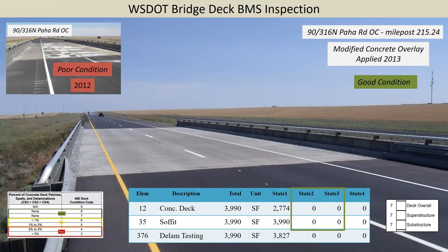This comes in really handy on my side of the equation when I'm trying to determine the 10-year needs for the whole state. So here again is that same bridge. It was in poor condition in 2012. We went in 2013, did a hydro mill and a modified concrete. So all those codes changed, and now the inspector would rate this as a good condition deck.